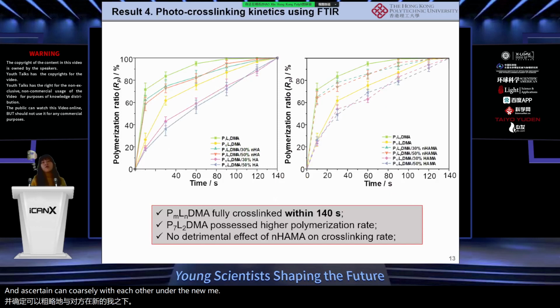And we also examined whether the incorporation of the hydroxyapatite nanoparticles will affect the polymer polymerization. We can see that all composites can be cross-linked within 140 seconds.